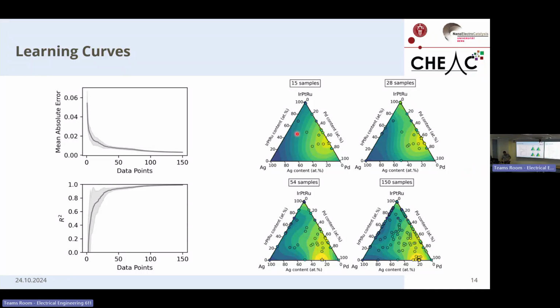So what we see is that the mean absolute error of this prediction is decaying exponentially. And around 50 experiments, we observe our first plateau, and it further nicks down at around 80, 90 experiments to, I would say, a space that is more or less the same as the DFT space that has been calculated. We can also visualize it using these ternary plots. And you can see that going from 15 experiments to 50 experiments, we have drastic changes in our contours. But the moment we go from 50 to 150 experiments, there are only minor changes. So we are just fine-tuning the space instead of observing new large changes in it.